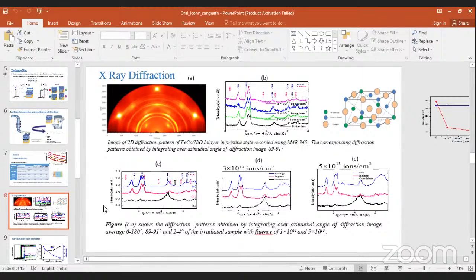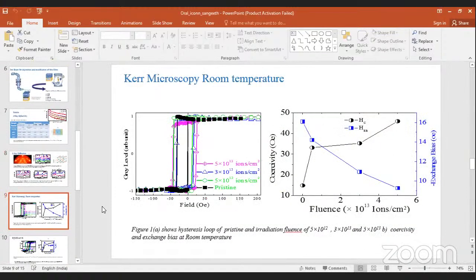The peak corresponding to the FeCo and NiO has shifted to lower angle sides, which means that the stress induced during the deposition has been relaxed after the irradiation. So while going to the magnetic studies, we field cooled the system from 550 Kelvin to room temperature to understand the exchange bias.